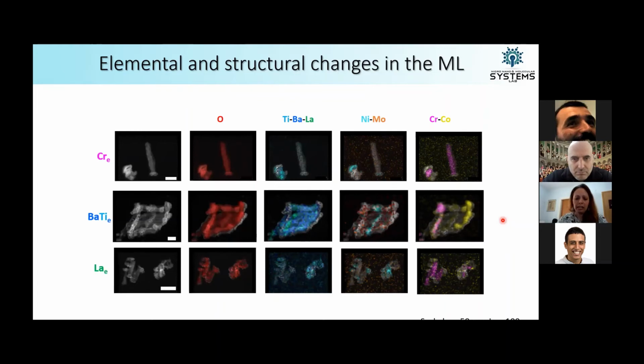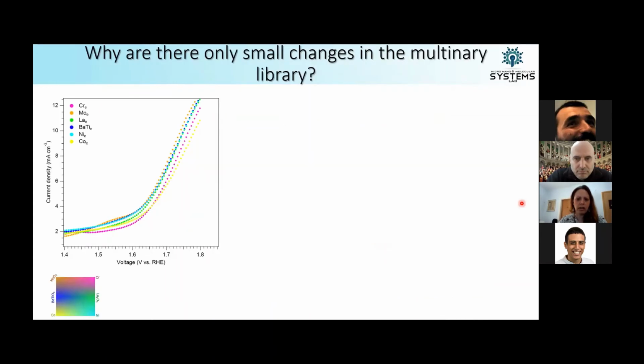So we then decided, okay, it's time to examine this interesting library that has really big compositional structures and really large nanostructural changes, and see what their oxygen evolution reaction capabilities are as an electrocatalyst or electrocatalysts, because it's a lot of different materials. So first glance, we can see these are just the different edges of the library, and they're marked over here so you can see what they look like. It looks like there's really no big changes on the library with regards to the overpotential that's needed for oxygen evolution, which is quite surprising because we would have expected large changes since we have both structural changes as well as compositional changes, so the chemical environment should have an effect.